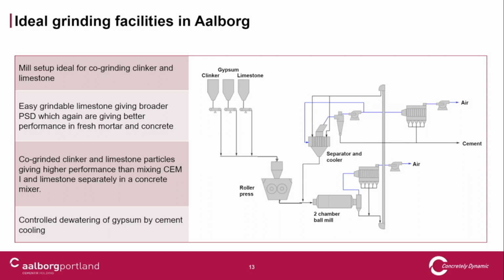Also, the separator is driven by cold air, so we are cooling the cement and controlling the dewatering of the gypsum — how much semi-hydrate will be in the final cement. That's also part of the varying properties of the cement.